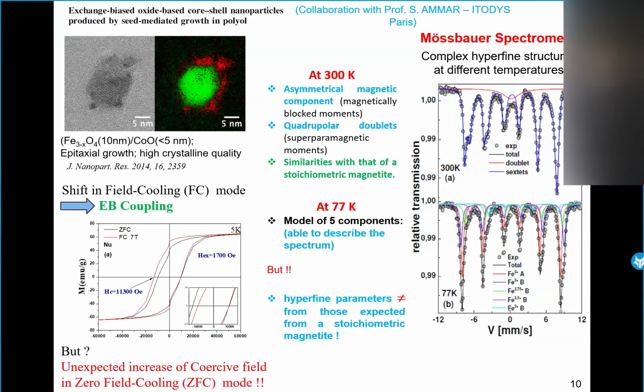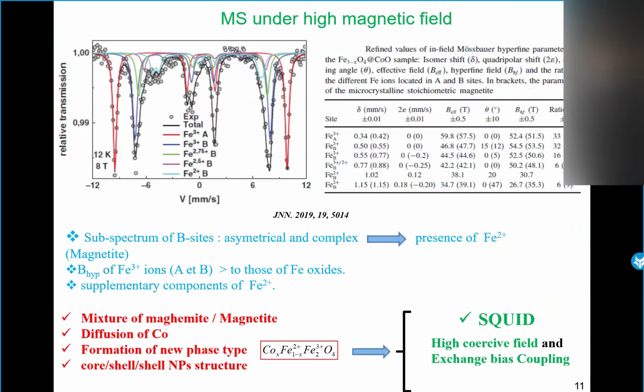Now in the measurement at 77 Kelvin, the sextets remain present. Normally for magnetite, we have a model with 5 subspectra, a model with 5 components. We arrived to reproduce the experimental spectra correctly using the 5 subspectra of iron oxide, but the hyperfine parameters obtained here are different from those expected for a stoichiometric magnetite. So now, in order to have more quantitative information, we applied an external field.